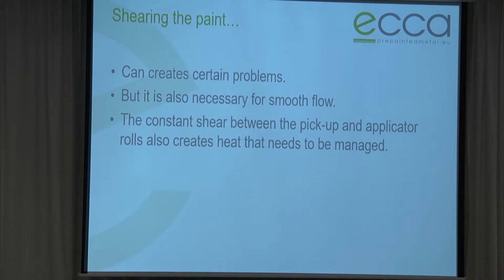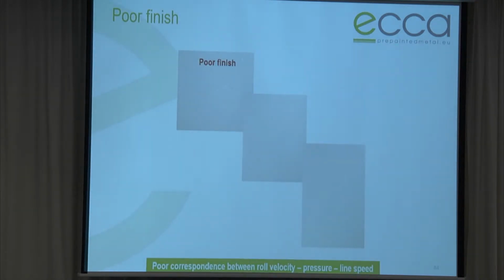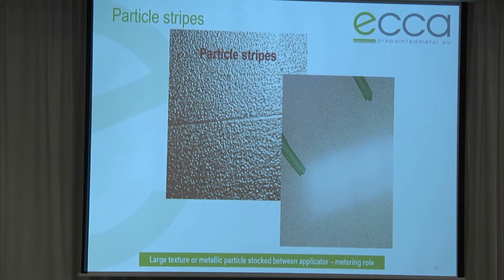So when you shear the paint, that creates certain problems, but it's also creating good flow because it brings the viscosity down. And these are probably difficult pictures to see. We do have a few panels up here, but you can control the appearance a lot by managing the differential speed between the pickup roll and the applicator roll, and then also managing the line speed itself.